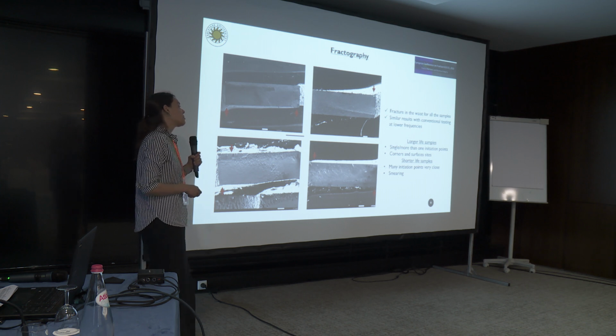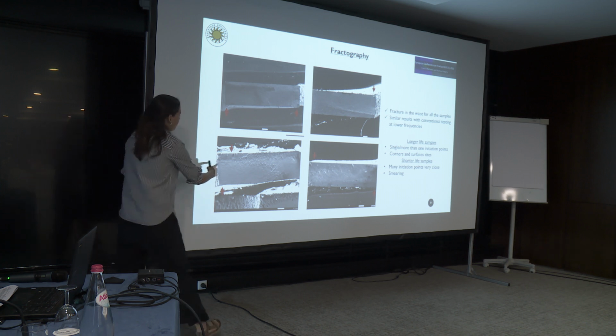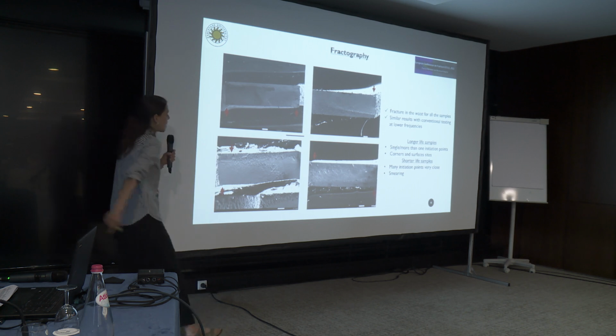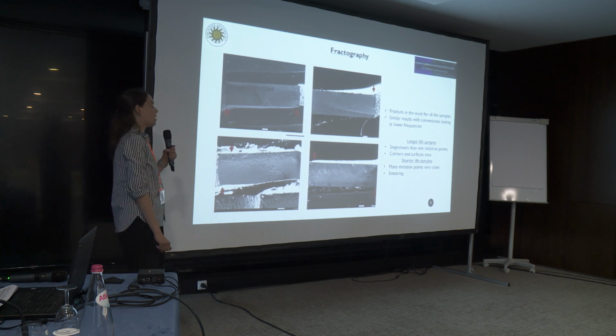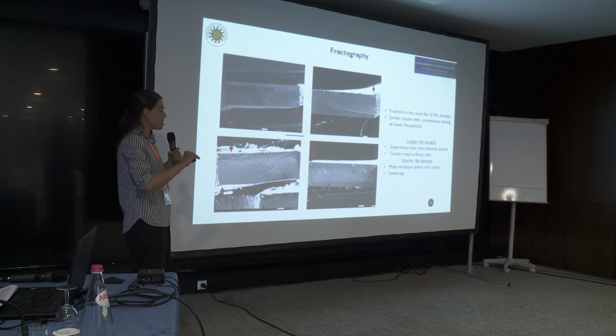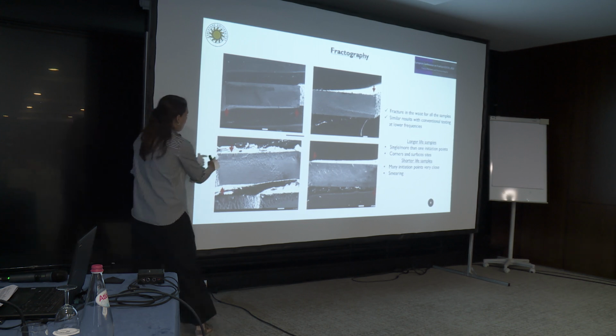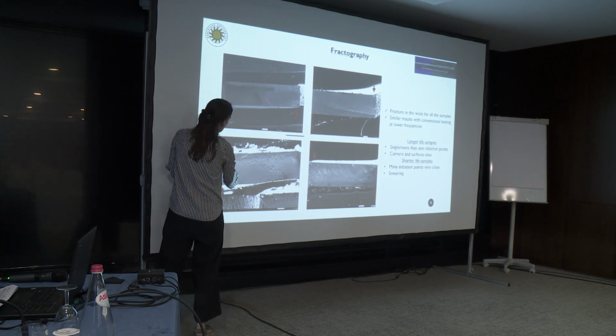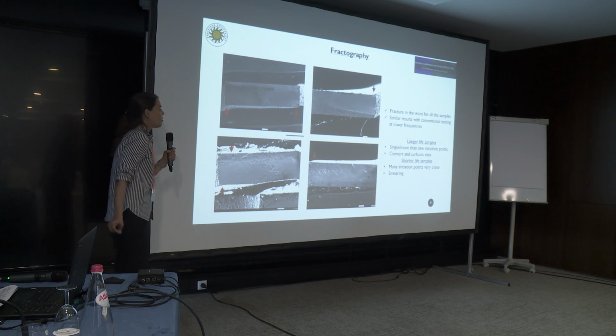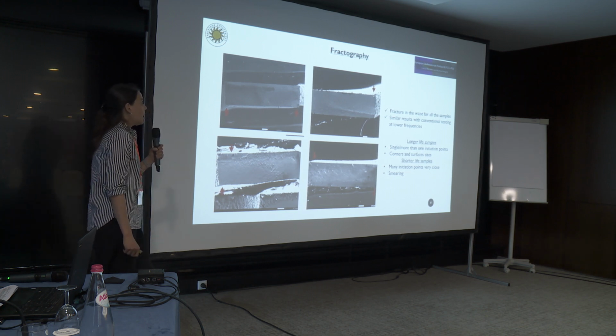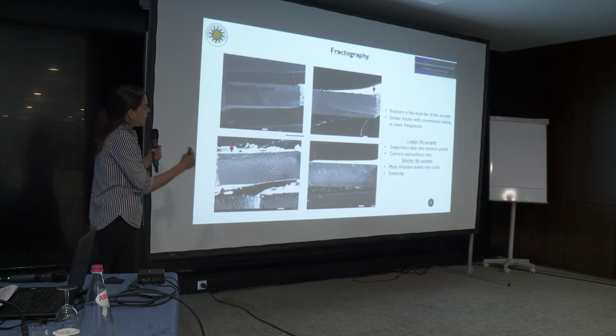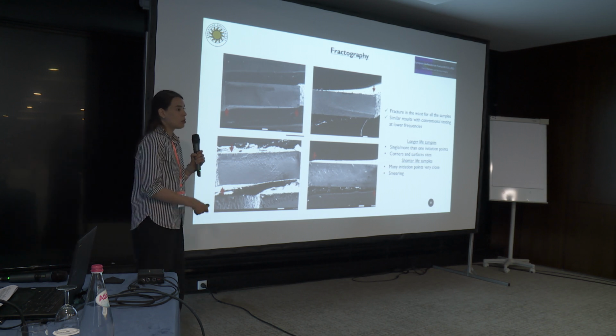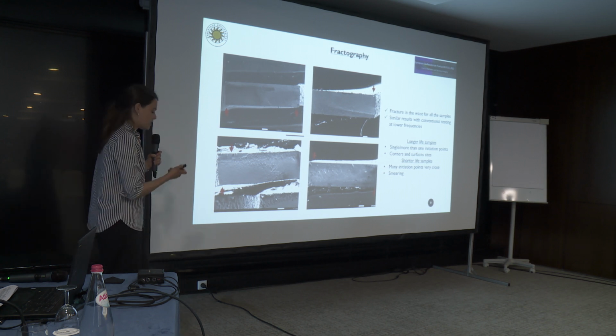Regarding the shorter life samples, this area over here was very, very common. It was always below the surface, and there are many small initiation points with small crack growth areas very close to each other. And of course, we had smearing because shorter life specimens mean higher stresses.